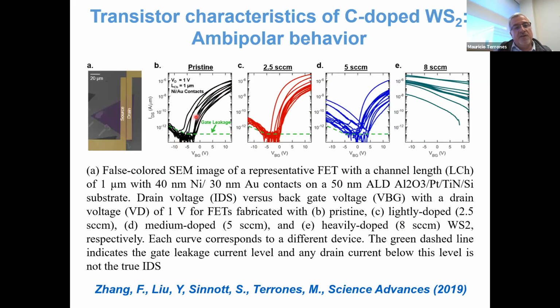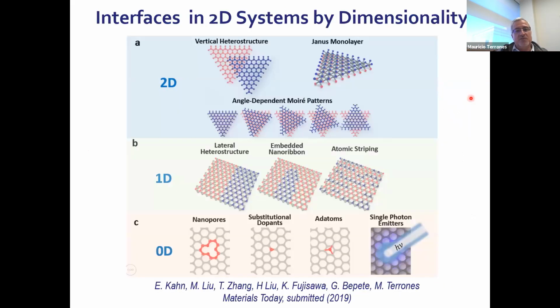So you have an N-type semiconductor, the tungsten disulfide here. And as you introduce more carbon, again, you start to see the P branch developing until this becomes a P-type. So this is very interesting, right? You introduce more and more carbon, and you completely change the electronic behavior. So this is another way of looking at the doping. And again, they are very different. You look at the periodic table, and then you start thinking about what else you can put in. And I think it would be interesting to look at those.